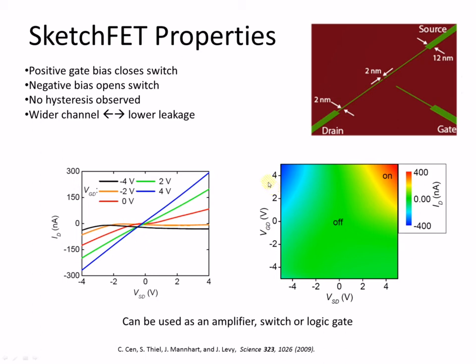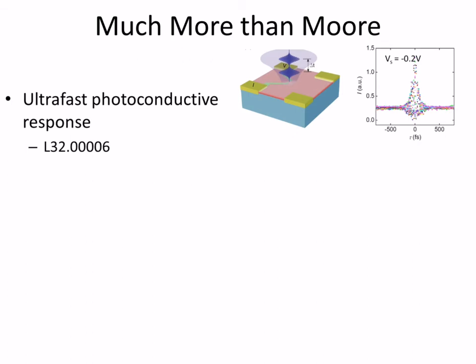As a transistor, this device can actually work at frequencies in excess of gigahertz. The initial reports maxed out at about 5-10 megahertz, but by making the leads less resistive, we were able to push the frequencies well into the gigahertz regime. So this material is much more than Moore in that there are many properties that are going to be of interest.